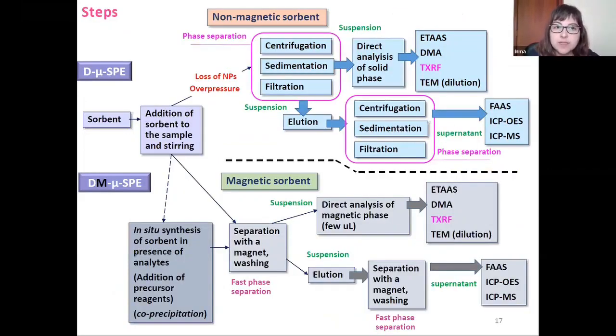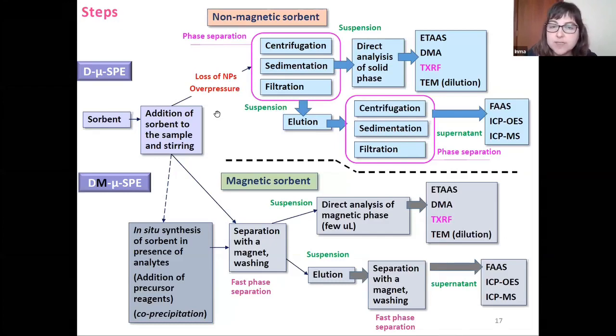In this slide, we can see the comparison of the use of non-magnetic and magnetic sorbents by these both techniques, dispersive micro solid phase extraction and dispersive magnetic micro solid phase extraction. As we can see in the first part, we see more steps if we use non-magnetic sorbents. For example, the phase separation is performed by centrifugation, sedimentation, or filtration. However, this step is replaced by a fast phase separation using the external magnetic field, usually 5 minutes of separation is enough for a complete separation of the magnetic nanoparticles from the aqueous solution.